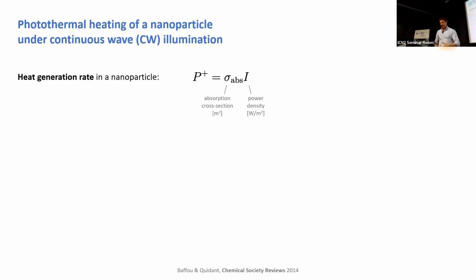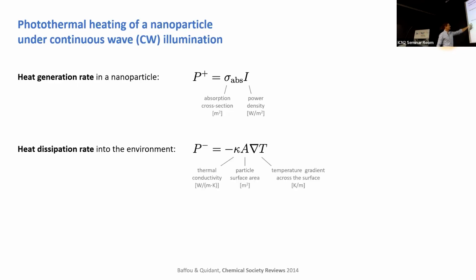Now, at the same time, the nanoparticle is getting hotter and hotter, and as it's getting hotter, it's dissipating heat into the environment. And this cooling rate also needs to be taken into account. And the cooling rate, or heat dissipation rate, depends on the thermal conductivity of the environment, the particle surface area in square meters, and the temperature gradient across the surface.